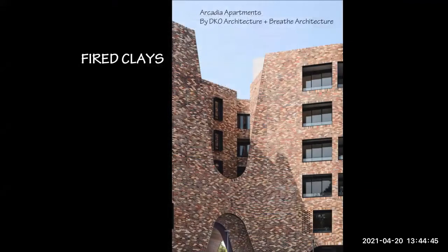Now, fired clay bricks are back in vogue. Austral Bricks have a small brick making plant at Longford in Tasmania that uses mostly sawdust from local sawmills to fire its kilns. To my knowledge, apart from the few bricks that are produced there, we're looking across Australia at around 660 megajoules of gas to produce solid fired clay bricks for 1 square metre of single skin brickwork. For the same 1 square metre of 90 millimetre thick solid concrete blockwork, it's only 240 megajoules. So in this emergency, until we can decarbonise the bulk of this very energy intensive industry that produces fired clay bricks, we need to use recycled bricks or other wall cladding materials where we can.